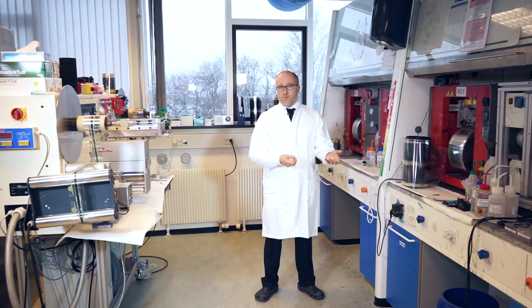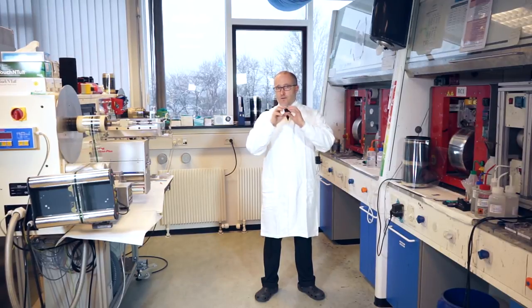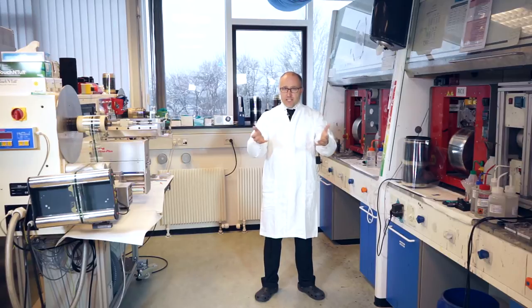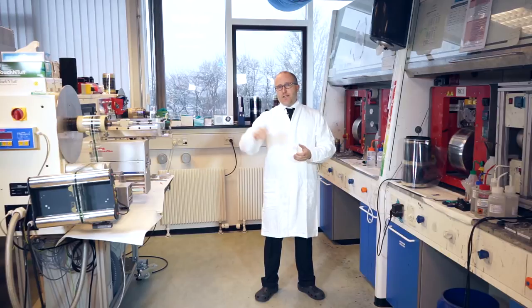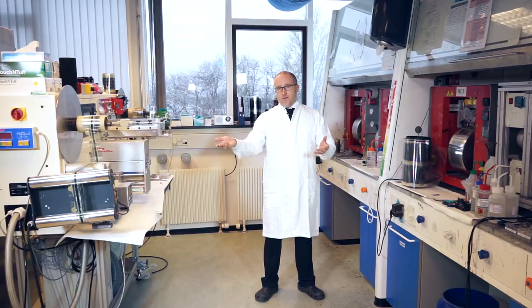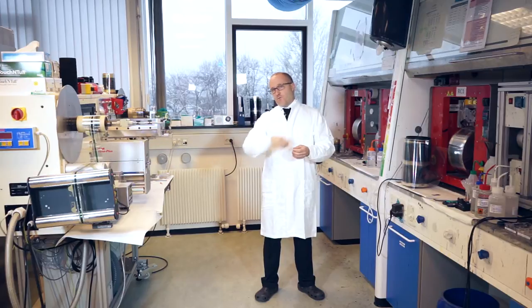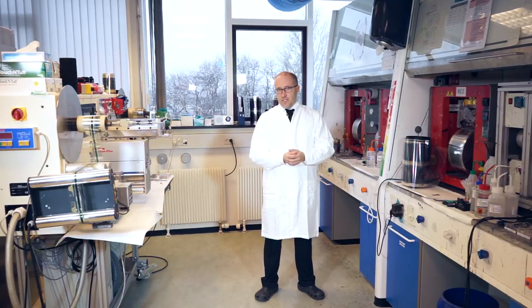Foil transport means that foil has to roll over support and guiding rollers where the electric field is static with one fixed value, and then it's transported typically in free air, suspended in air through the tension of the web to the next roller through the machine. And there's typically many rollers in such a machine, and the static fields may change a lot. And this is particularly challenging for wet films, as I said earlier, with low viscosity that in principle can move around. There's no reason the ink shouldn't move in response to a static field.